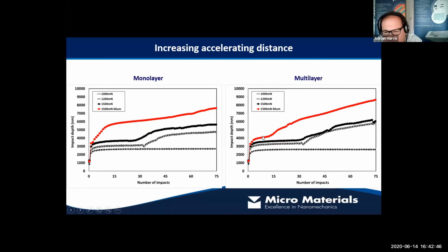So we still get some low rate of deformation taking place for a period of time before our failure starts, whereas here we get the initial plastic deformation taking place in the first few impacts, and then the failure is almost immediate. So there's some differentiation possible there between these samples in impact at room temperature.